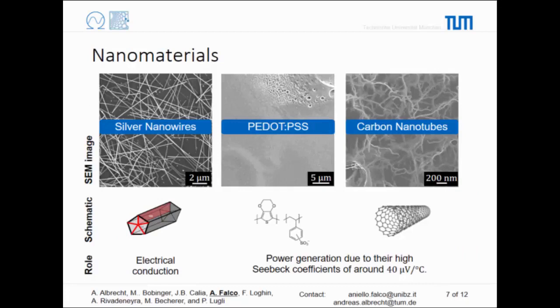And we could employ all of them in couples, for instance, and exploit their difference in the thermoelectrical potential. The silver nanowires are not famous for their high Seebeck coefficient. Actually, they have quite a low one, but they're the best semi-transparent material that we could have access to, so best in terms of conductivity. So from this point of view, we chose that in order to then bring the charge to the other side of our structure. PEDOT:PSS and carbon nanotubes, and in general carbon-based materials, are on the other hand characterized by very good Seebeck coefficient.